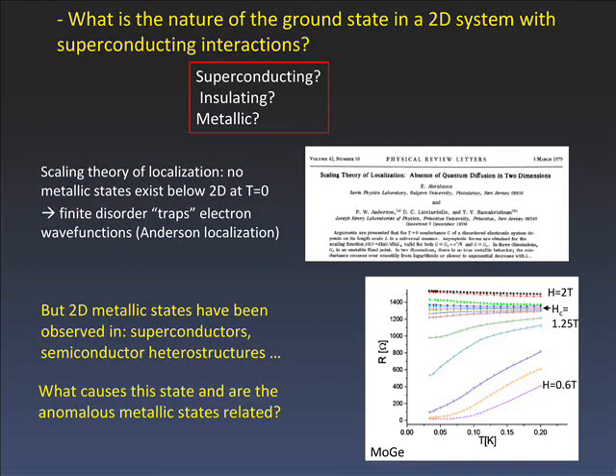One of the questions we've been asking is: what is the nature of the ground state in a 2D system that has superconducting correlations? It seems like a basic question, but it turns out to be complicated. According to the scaling theory of localization, as you go to low enough temperature in 2D, any small amount of disorder should trap all your electronic wave functions and lead to an insulating state. As you approach zero temperature, you can have a superconductor or an insulator, but you should not have a metal — theoretically.